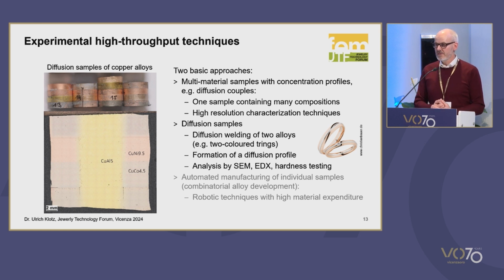And we are doing just the same, and this is an example that we did on copper alloys. So you see these samples in the top image. There are 4 or 5 rings, and you can see from the color that these rings have different composition. And in the lower image, you see the cross section. So you see the 4 rings, and in the center there is a cylinder, and these rings and the cylinder are bonded together by diffusion bonding, so that they're in intimate contact, and so that diffusion can take